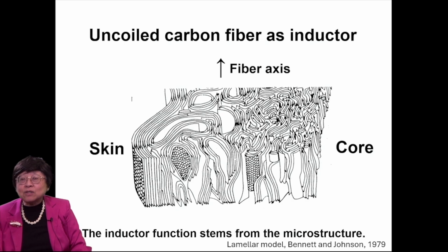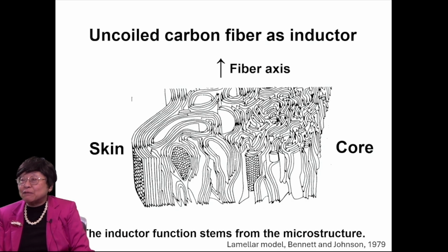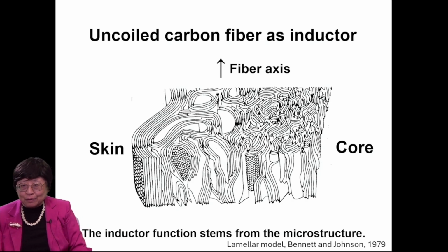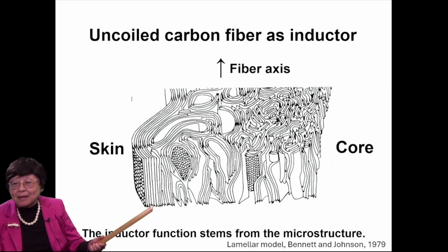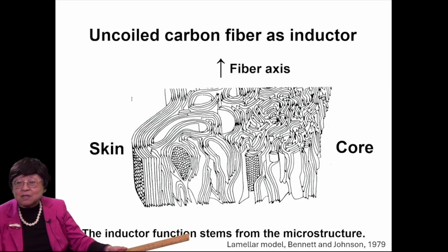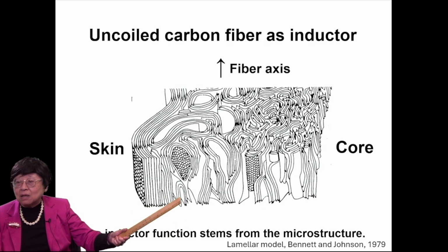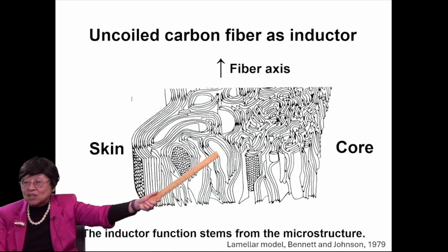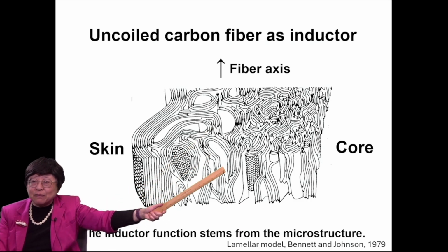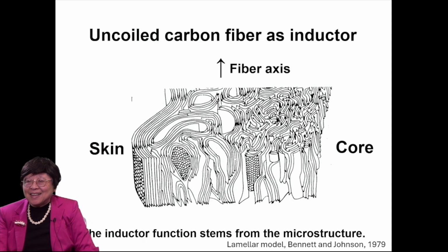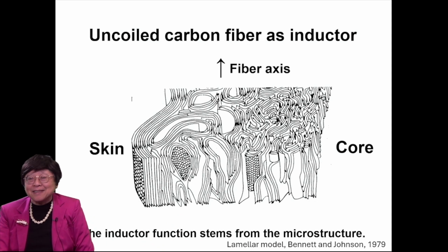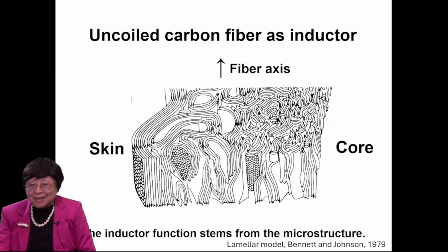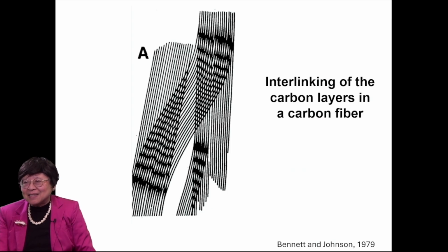So uncoiled carbon fiber, we discovered to be an inductor. And that inductor function stems from the microstructure of the carbon fiber. You can see these carbon layers inside a single carbon fiber. They're crooked, okay? It's not coiling, but it's a bit like coiling. And this is another rendition of the microstructure, showing interlinking of the carbon layers within a carbon fiber.